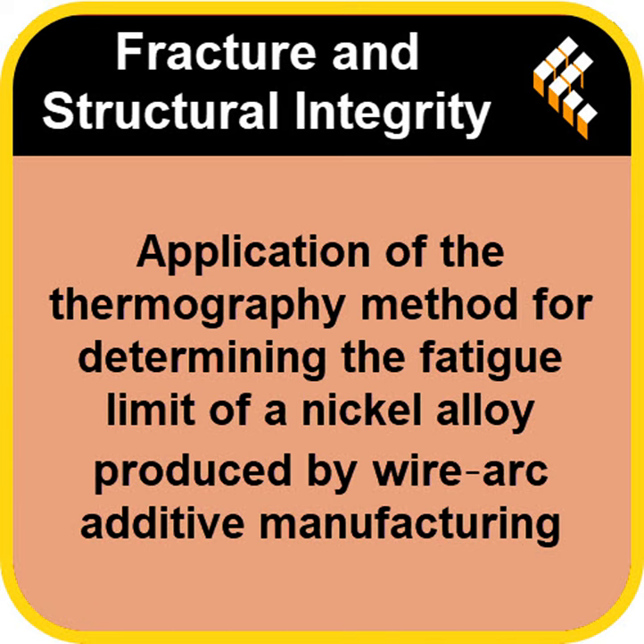I love this detail from the source material, though. For all this high-tech equipment, they still had to coat the specimens in simple black matte paint. It sounds low-tech, but it's so important. Different surfaces reflect infrared light differently. By coating everything in a standard black paint, they ensure a uniform emissivity. Basically, every sample radiates heat in the exact same way, which eliminates measurement errors you'd get from a shiny or uneven surface. It guarantees consistency.